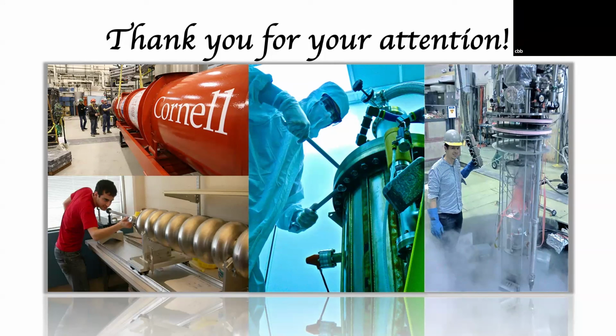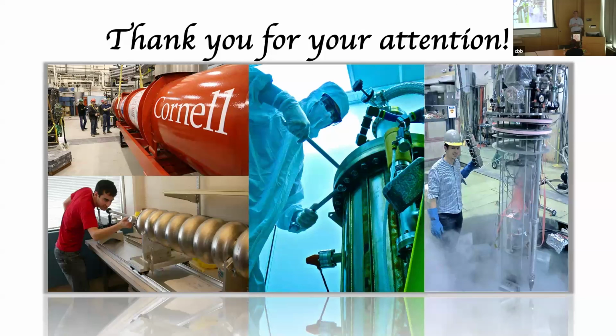When we have normal RF cavities, they need to be conditioned, and we have breakdown happening. I imagine if I have breakdown happening in an SRF cavity, it's pretty not good. We would be in trouble, yes. Is this not a problem because the fields are not high enough, or because they're cryo-cooled? The fields are decent fields, but I think the way we clean the cavities is different. We go through clean rooms, we high pressure rinse these cavities. So we are actually limited much earlier.